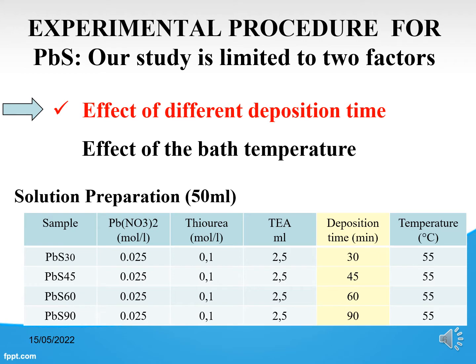Experimental procedure for PbS. Our study is limited to two factors: the effect of different deposition times and the effect of bath temperature. The solution contains lead nitrate and thiourea, which were used as sources of lead and sulfur ions respectively. TEA is used as a complexing agent. The deposition times were 30, 45, 60, 90 minutes, while the temperature was fixed at 55 degrees Celsius.